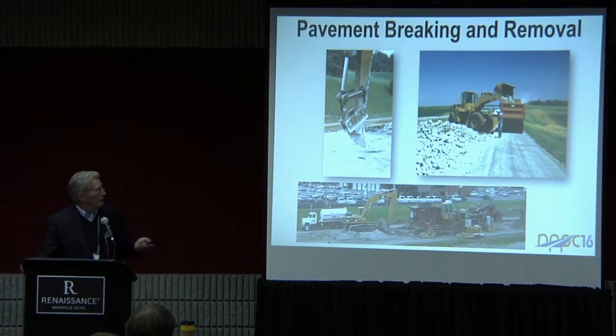Pavement breaking and removal now, using the rhino horn to kind of loosen those pieces that have been fractured and broken out. End loader to put it into the truck and haul it to an off-site place, or doing it right on the job site. And we're seeing a lot more in-place recycling of concrete being done now, where you got basically a portable crusher being used. The stuff's been broken up, using a backhoe to drop it into the crusher here, and a couple of different windrows being set up, one for coarse material out to the right, and you can kind of see one for fine material going out to the left. Windrowing those off to the sides and using them on the job site as required, usually back into a base application.